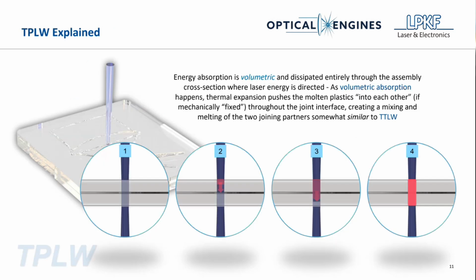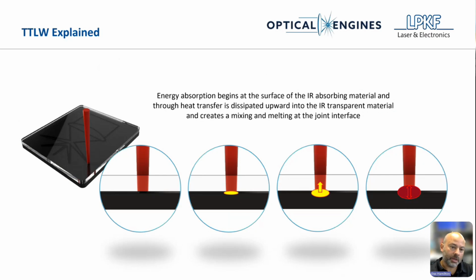All right, so TPLW explained. This is a graph showing the steps of the laser material interaction. It's two pieces of plastic stacked on top of each other in lap joint form. We start to shine the laser beam, and the plastic starts to interact with the laser and heat up, and then slowly forms this volumetric heat absorption down through the two pieces of plastic, with the result being this volumetric complete heating throughout the plastic. In contrast, in through transmission laser welding, the laser is absorbed first by the lower piece that's IR absorbing. The heat and conduction starts at that layer, and then through heat transfer, that heat is transferred up and creates a melting and mixing due to thermal expansion in the middle of the joint there.